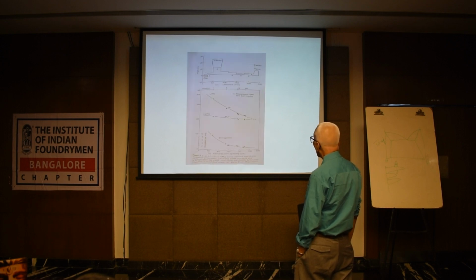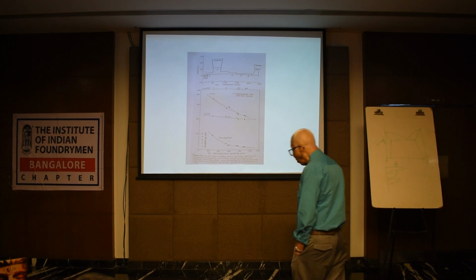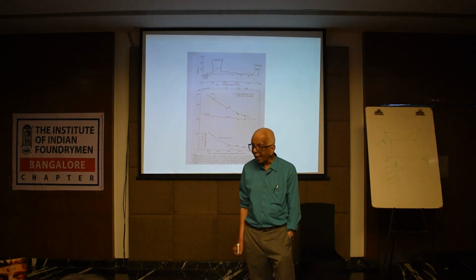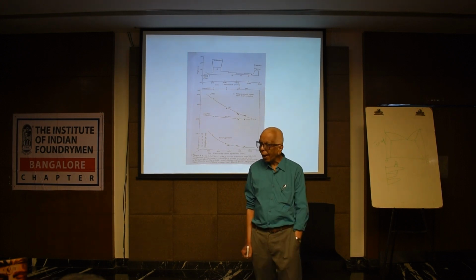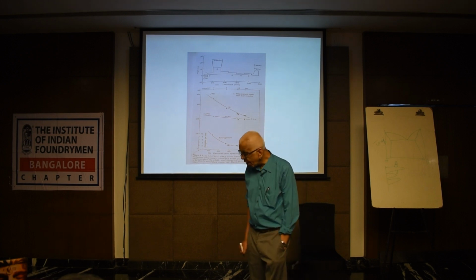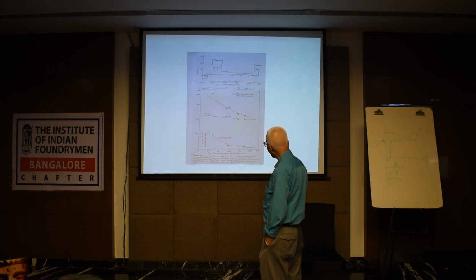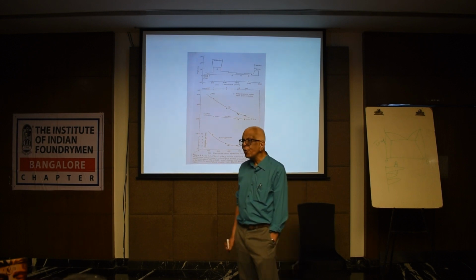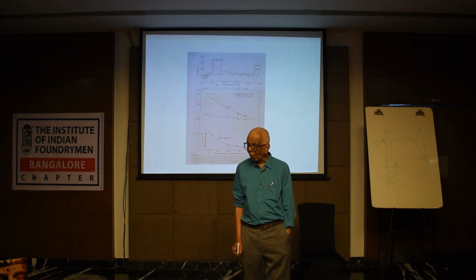Next slide, please. This shows the feeder and in-gates. What I would like to point out, which I saw long back, 40 years ago, when I was working in my father's company, is that in the gating system, you have two ratios. 1:4:4 is a pressurized gating. 1:4:10 is a non-pressurized gating system. If you use non-pressurized, the bifilms are reduced.